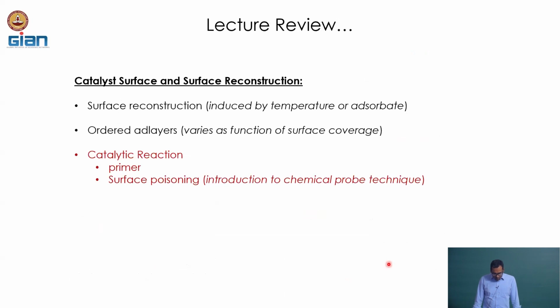Okay, so let's review a little bit what we have covered so far. Surface reconstruction happens, so the surface cannot be considered rigid, and this reconstruction can be induced by temperature as well as by the adsorbents. The adsorbents on the surface can be disordered layers or ordered layers, and their ordering varies with the surface on which they are grown, the coverage of the surface, as well as the temperature. Next, we will go into a primer on the catalytic reaction as well as the surface poisoning phenomena, and how we can implement a very niche chemical characterization technique to identify the surface poisoning and then to suppress it.